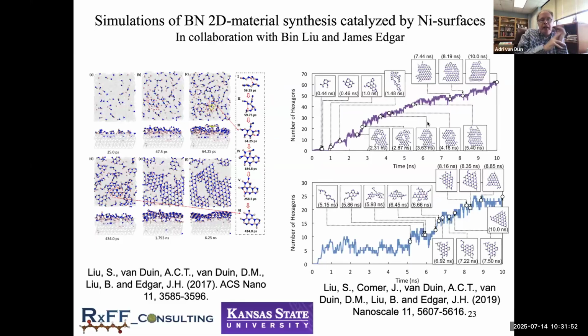And then this was just gas phase. Now, if you want to grow on the surface, that's fine. We have actually, within our company, managed to extend this towards a nickel borate structure, nickel chromium structures. So now we do exactly the same simulation, but we now have a 2D metal available. And you can see that previously we saw only a small amount of 2D boron nitride. Now the presence of the nickel really drives the system towards the 2D structure. And we can just very cleanly see which particular structures occur at which particular time scale.